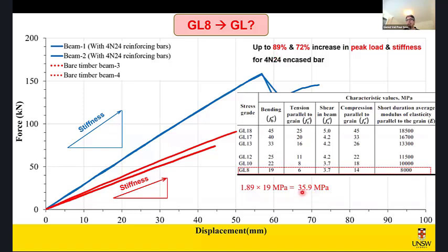Now, the bending strength is equivalent to 35.9 or 36 MPa, roughly. And in terms of stiffness, which is similar to, let's say, elastic modulus, if you want to convert them, 1.72, that 72% improvement led to this elastic modulus of 13,800 MPa. Now, if you look at this table, you will see it's equivalent or even above GL13. So you'll see by adding 4 and 24 bars, we converted GL8 to GL13.